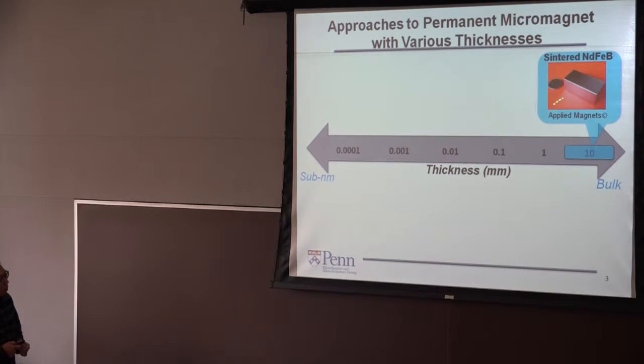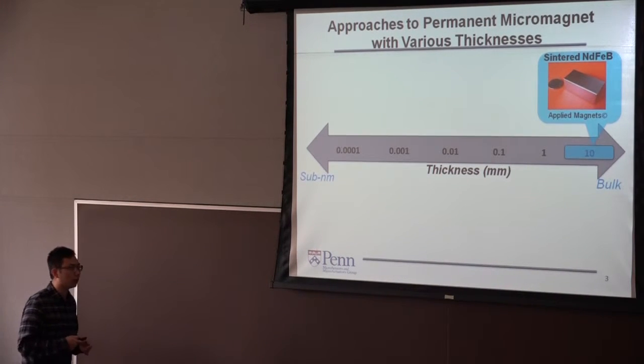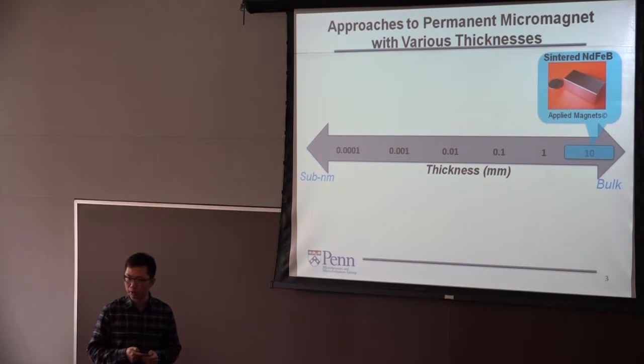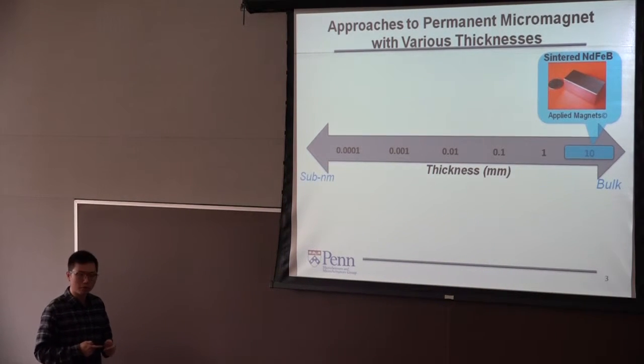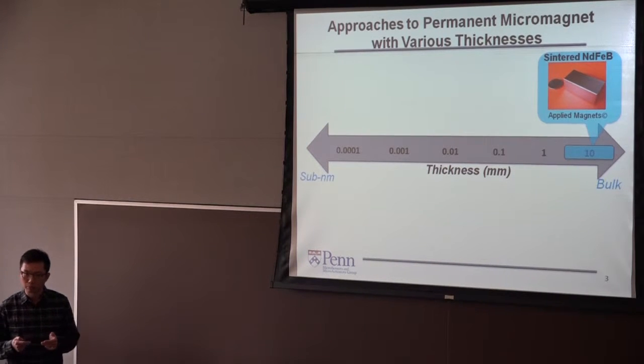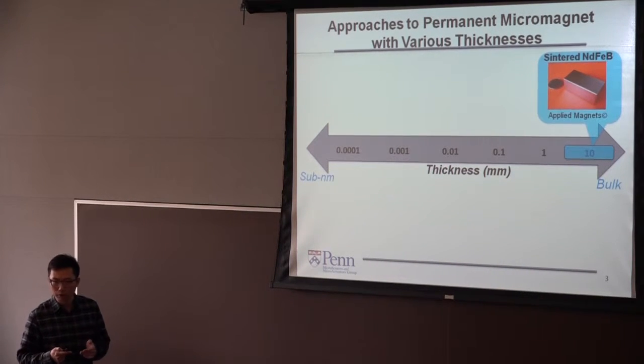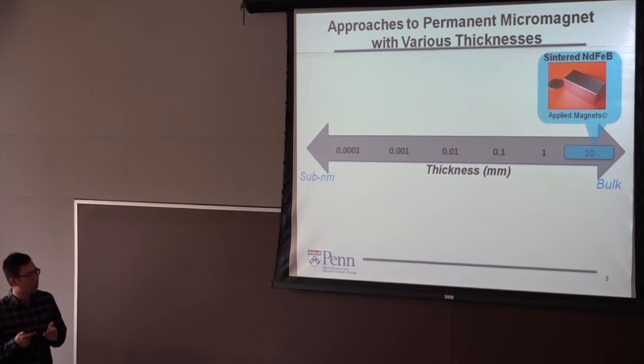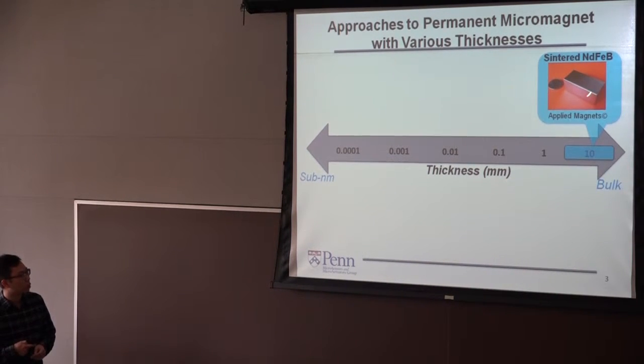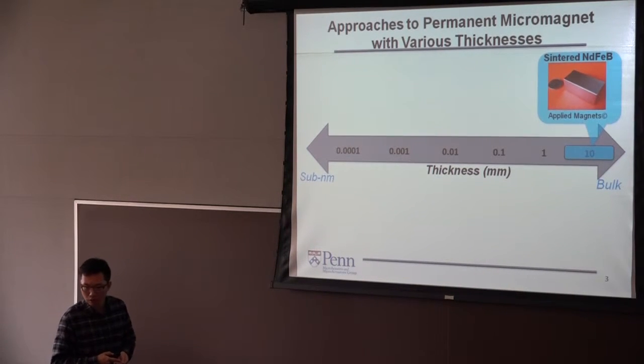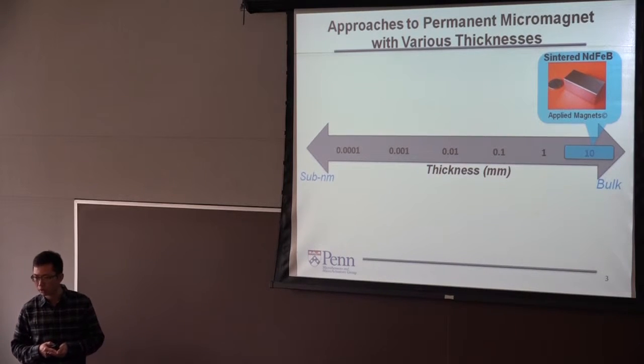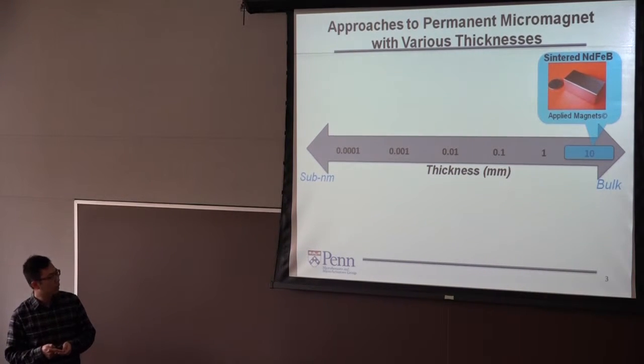So in the bulk scale, sintering by powder metallurgy is definitely one of the dominant techniques. You have molten alloys in basically a protected environment in an inductive furnace, and you melt it up, and then you pour it into a mold. Once it's solidified, we have this kind of bigger shaped magnet. Apparently this high temperature, normally 1,000 degrees C, is incompatible with the CMOS process, right? But more importantly, I think the scale is too big for MEMS devices.